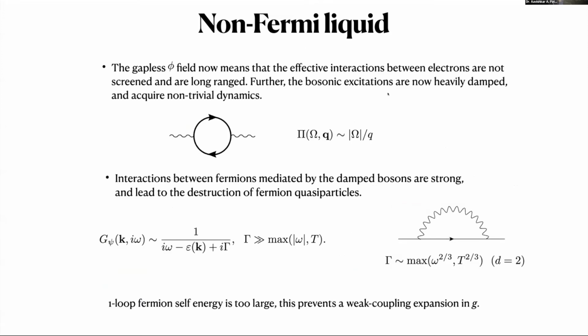Once you couple your fermions to this phi, if you just do field theory at the one loop level, these bosonic modes get damped, and that leads to a large self energy for the fermions. The energy dependence of the fermion scattering rate is parametrically much larger than just the excitation energy omega of the fermions. So even if the prefactor of the diagram leading to the scattering is small, since you have a parametrically larger quantity, it always dominates at low energies, and that prevents a weak coupling expansion in the fermion boson coupling.